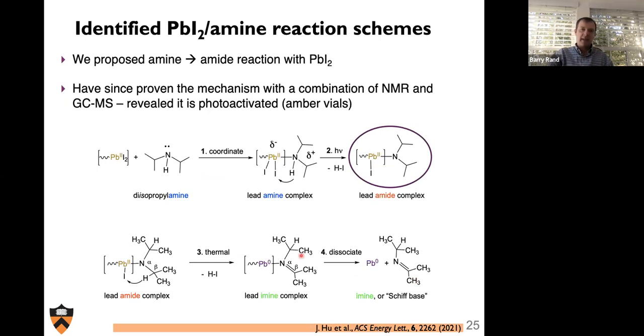And what they found was that lead iodide will, unsurprisingly, owing to the fact that amines have really strong donor numbers, coordinate. So you get this coordination complex between amines and lead-2, which forms spontaneously. The step that was underappreciated is the next one, which is the formation of the lead amide bond. And that one is photo-initiated. So the presence of a photon with the coordinated lead amine complex results in this lead nitrogen bond. And it turns out that this type of lead amide complex, shown here in more detail in the lower left, has what's known as a beta hydrogen. So either of these carbons, beta to this amine nitrogen, have considerable hydrogen right next to them, and this hydrogen can eliminate the iodide that's bonded to lead-2 in the presence of any amount of heat.